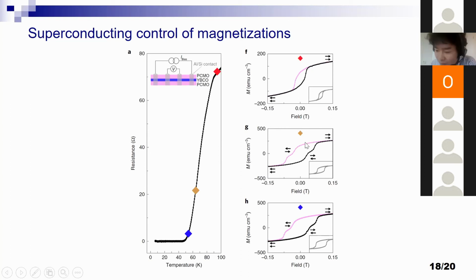So YBCO interlayer here wants to align the two PCMO layers to become antiparallel. So superconductivity of YBCO is here creating an antiparallel phase of these PCMO layers. So if we use this kind of exchange interaction, potentially we can switch magnetization of ferromagnet using superconductivity.